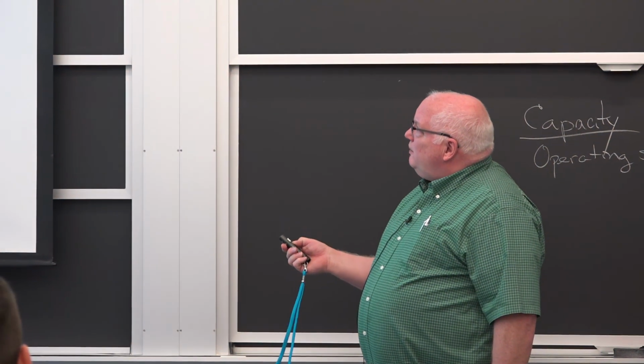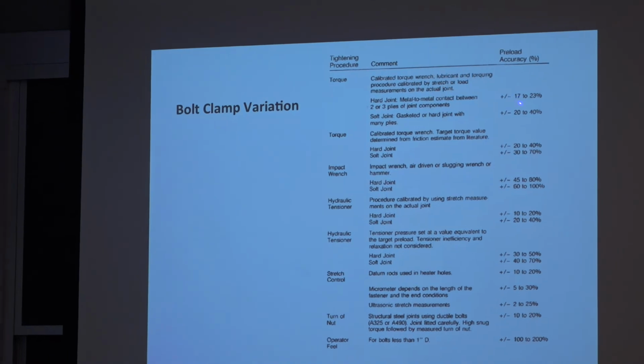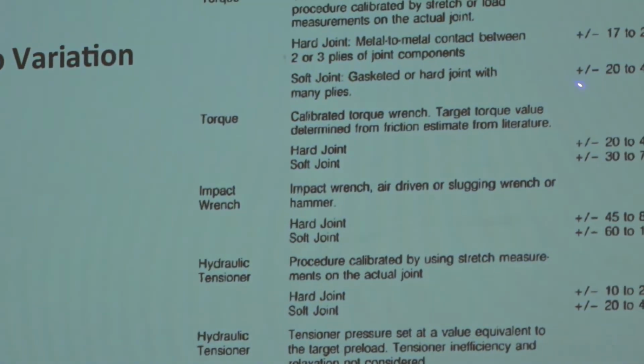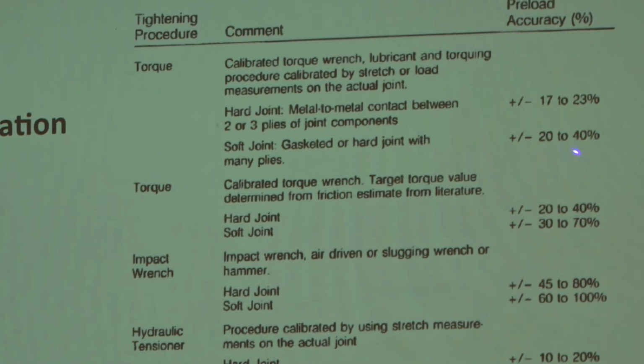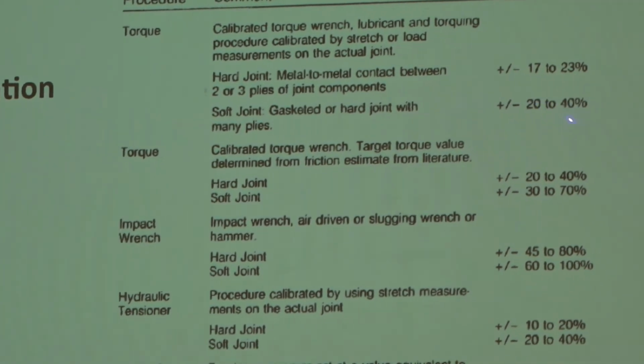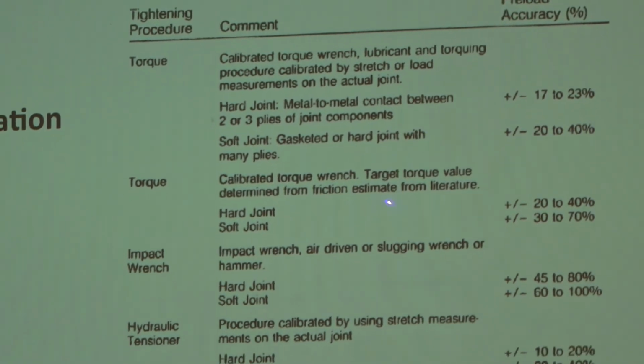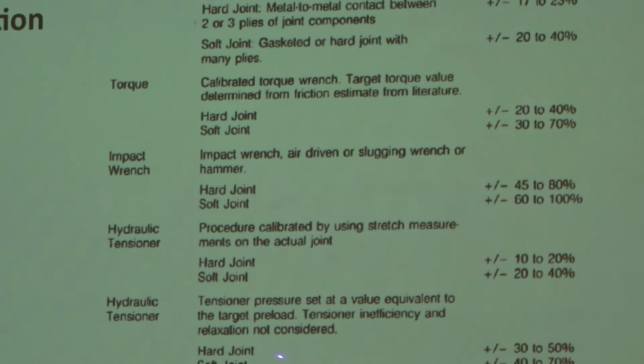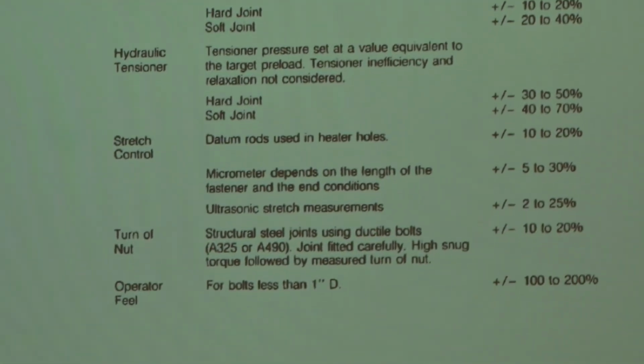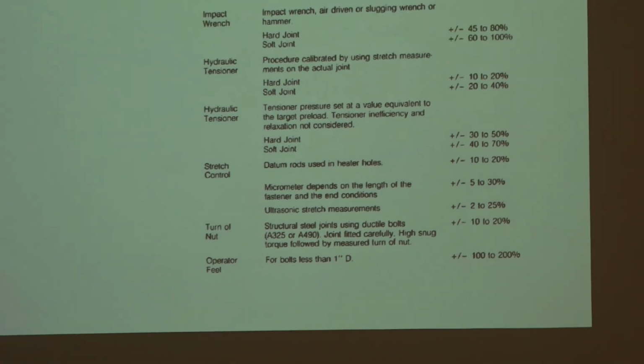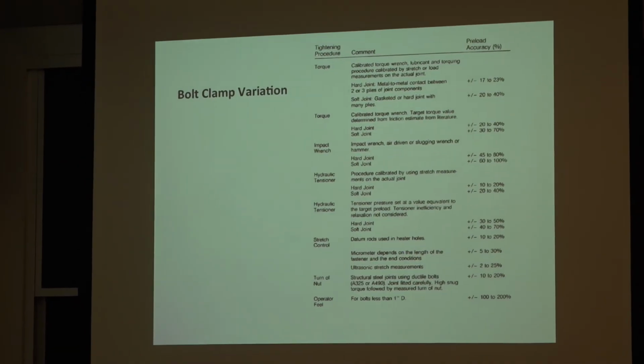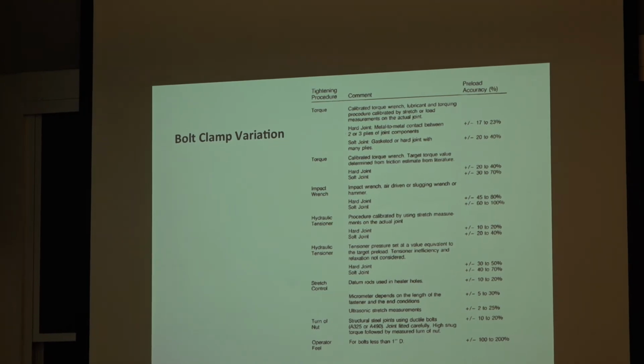But anyway, here's something Bickford did for the Nuclear Regulatory Commission. Bolt clamp variation, calibrated torque wrench, plus or minus 17 to 23%. Hard joints, soft joints, which is the compliance of the joint, plus or minus 20 to 40. That's my plus or minus 30, I said. And you can use torque wrenches, impact wrenches, hydraulic tensioner, stretch control. Stretch control is measuring the elongation of the bolt with the micrometer, right? Now they actually use ultrasonics to measure the stretch of the bolt. You can measure the length of the bolt fairly precisely before and after tensioning, so far as that goes. But even stretch control, plus or minus 10 to 20%.